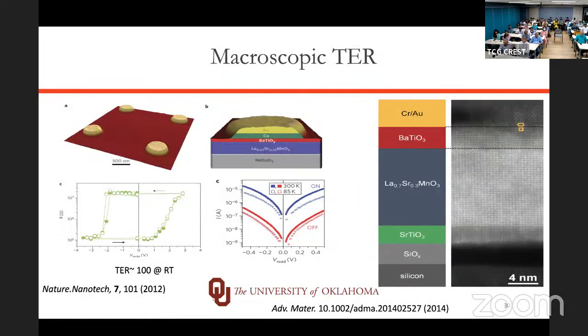So in a ferroelectric tunnel junction, you will have a top metal, a ferroelectric like barium titanate, and a bottom metal. There are a lot of other layers in between, but for now you can ignore them. So it's essentially metal, ferroelectric, metal. You're looking at the vertical transport, and it's a tunneling process. And that gives you a hysteresis loop like this. So essentially, as you change the voltage, the resistance exhibits two distinct states.